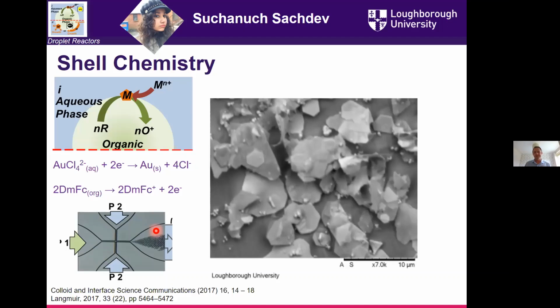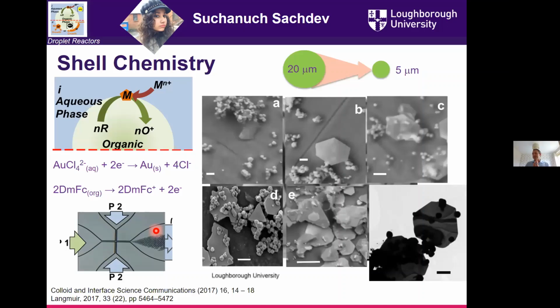And then she eventually managed to convince me. She's very patient and didn't use too many horrible words in trying to convince me that I was not right and that this was actually gold. And we'd done the elemental analysis, and what actually was happening was we were making these wonderfully large platelets of gold via this process, and it was completely unexpected. And not only were we making these platelets, but it turned out what we made, i.e. the shapes and the sizes, was dependent upon the droplet size.